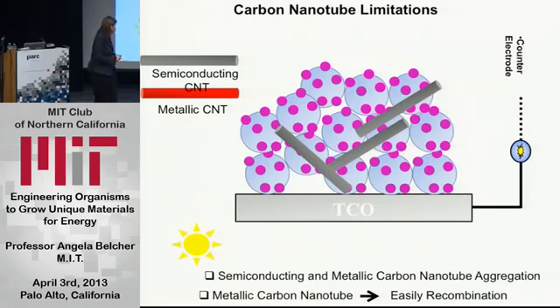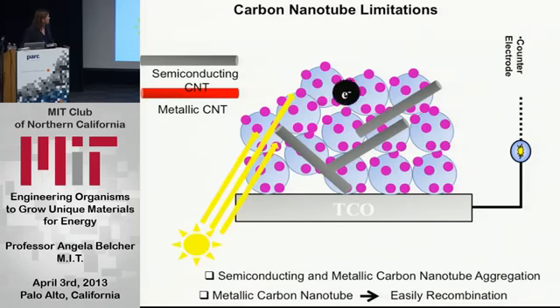And basically what we wanted to be able to do was to shine light and have the electrons find a carbon nanotube and have a more direct path. So you could still have a higher dye loading, but you could have a more direct path. And we wanted to compare semiconducting carbon nanotubes versus metallic carbon nanotubes as well, because as we found out, it was the metallic carbon nanotubes that were actually decreasing the overall efficiency in what people had tried before.